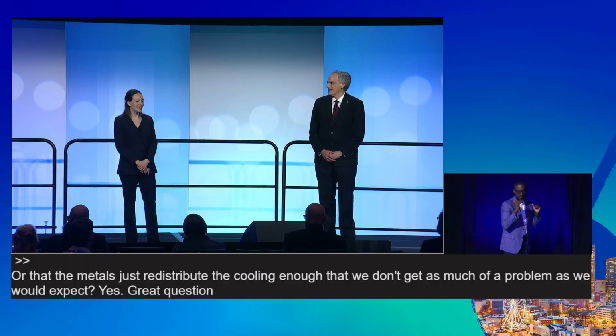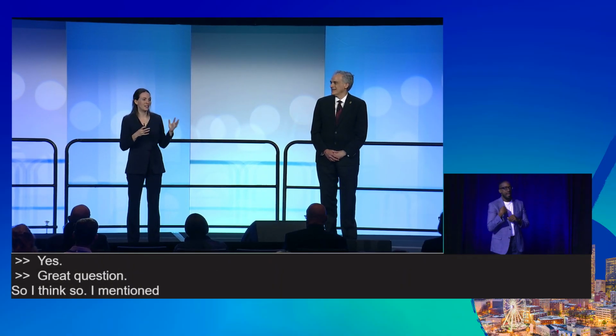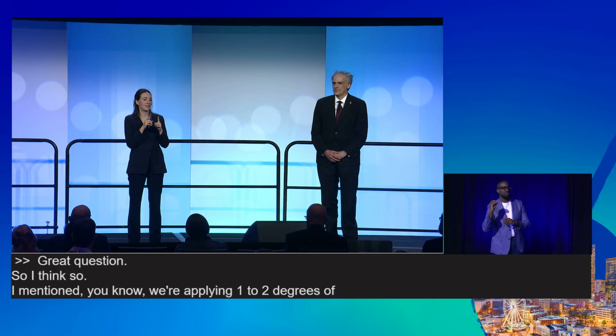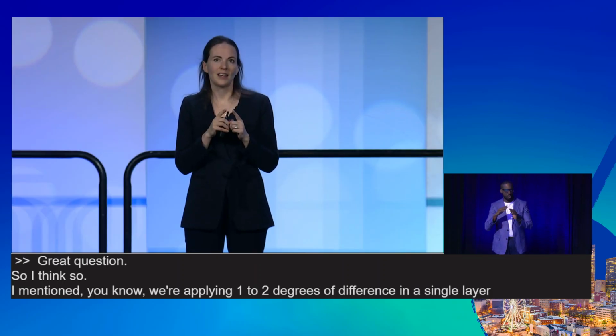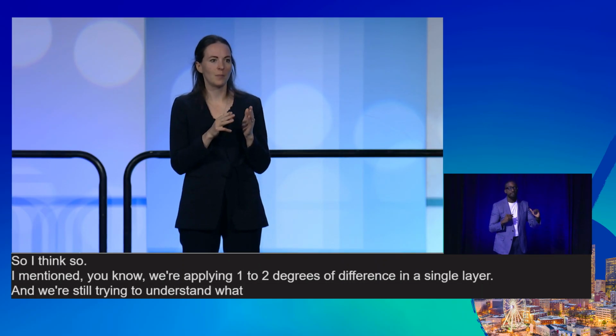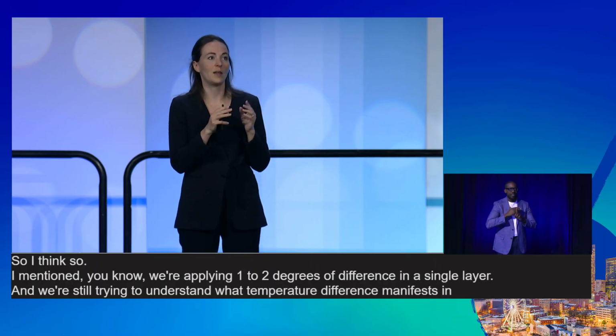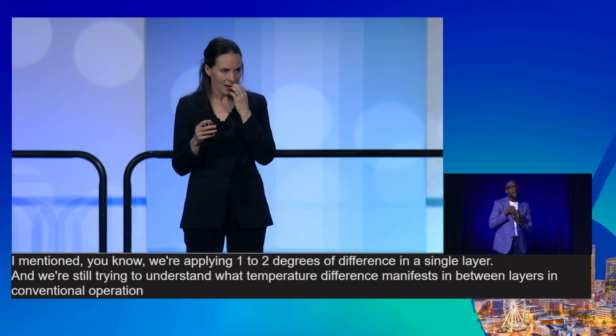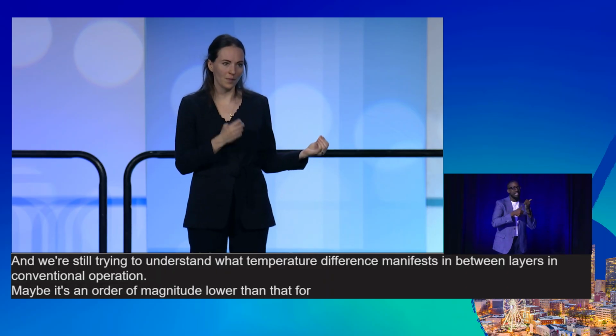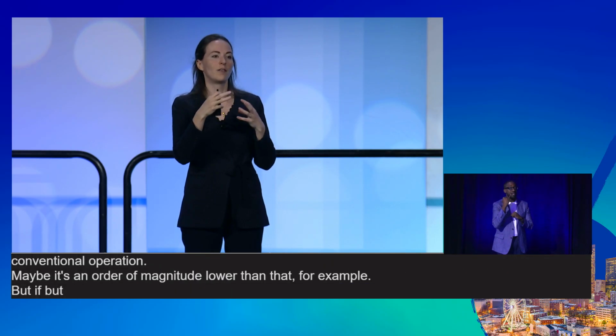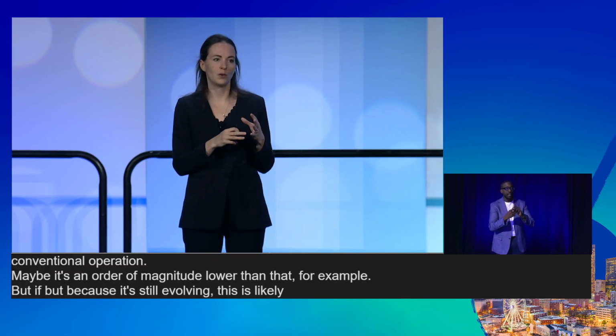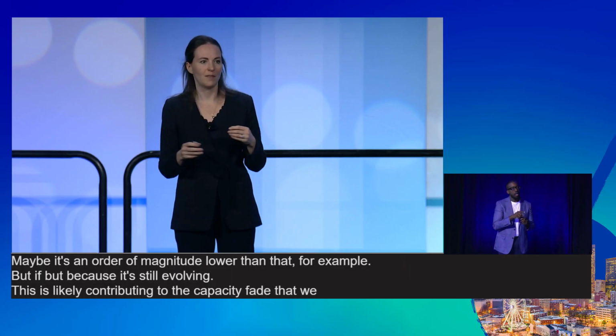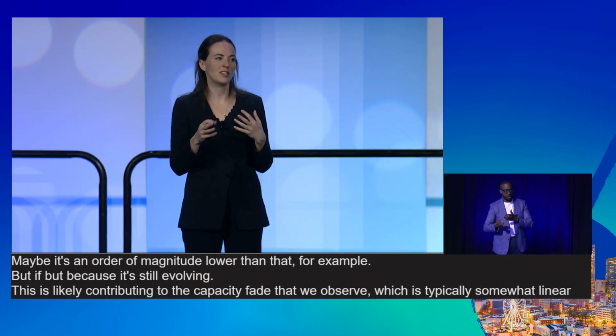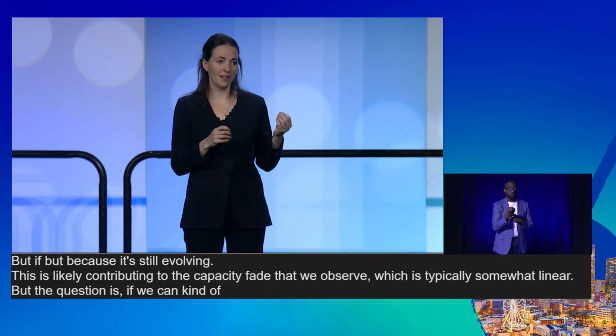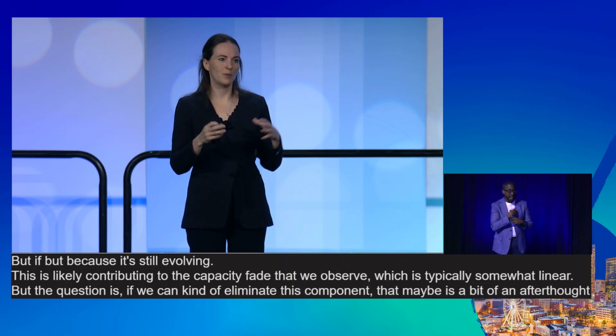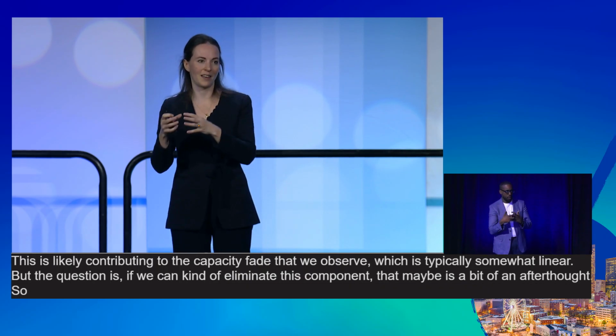Yes, great question. So I mentioned, we're applying 1 to 2 degrees of difference in a single layer. And we're still trying to understand what temperature difference manifests between layers in conventional operation. Maybe it's an order of magnitude lower than that, for example. But because it's still evolving, this is likely contributing to the capacity fade that we observe, which is typically somewhat linear. But the question is if we can eliminate this component that maybe is a bit of an afterthought. So we apply cooling after we design the cell.